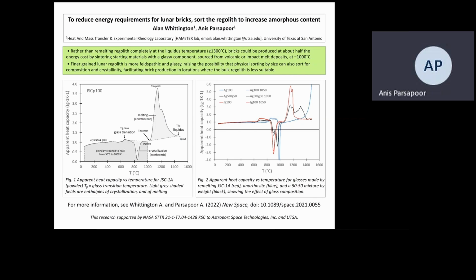For example, 1564 joules per gram for remelted JSC-1 and 1670 joules per gram for a 50-50 mixture. In addition, sintering can produce crystalline samples without needing to heat much above 1000 degrees, and the release of latent heat of crystallization makes this a very energetically efficient approach, with total enthalpy as low as about 800 instead of 1670. Therefore, bricks could be produced at lower energy cost by sintering starting materials with a glassy component sourced from volcanic or impact melt deposits at about 1000 degrees.